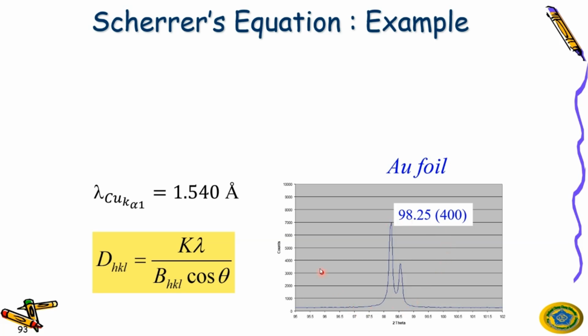And if I show you there are only two peaks in this region from 95 degrees to 99 degrees, you got this peak, right? The angle is 98.25, and the plane is 400. So first of all, if you use this equation, I will tell you the K is 0.89, not 9, it's 0.89. Okay, and I also told you that the wavelength of the X-ray is copper K alpha 1, which is 1.54 angstrom.